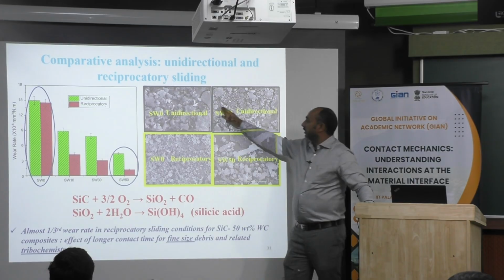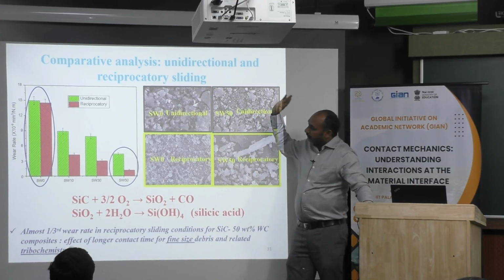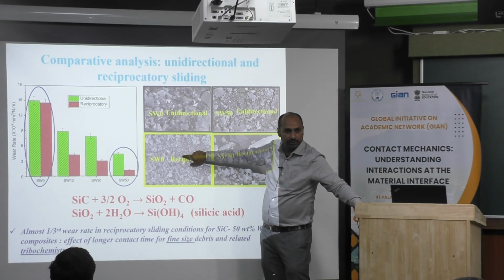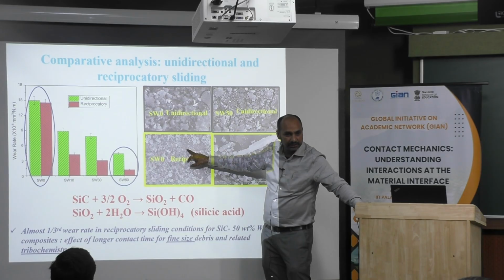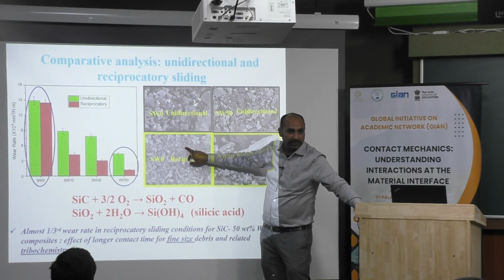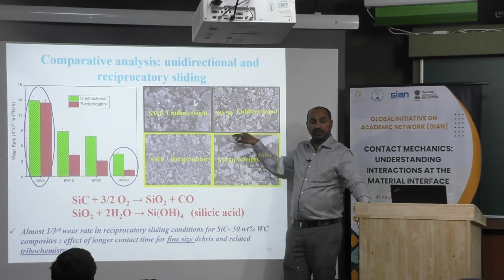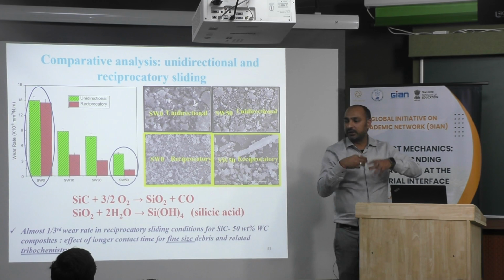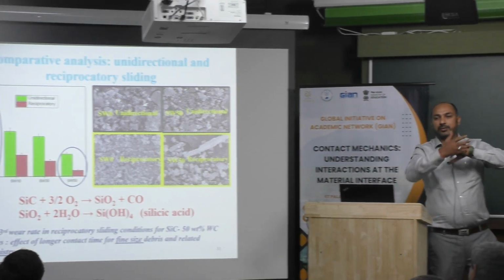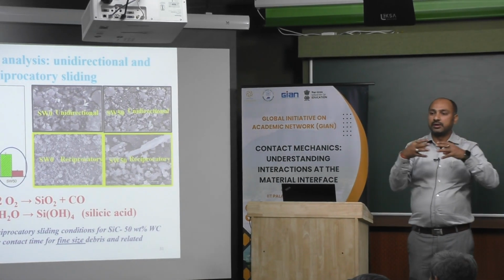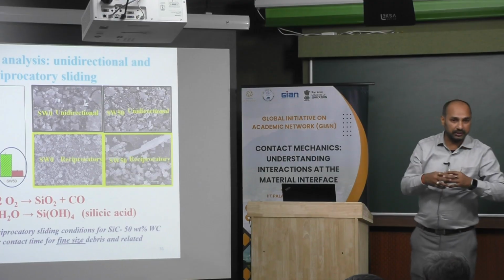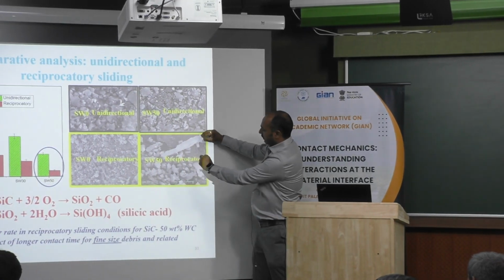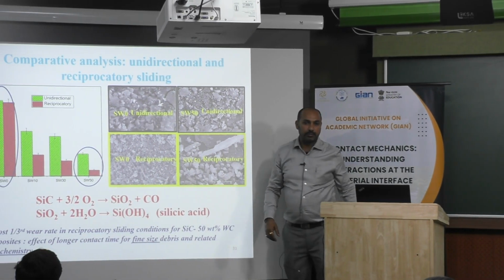We are simply seeing a reduction in debris size. Now by changing the configuration, the debris size for SW0 is decreasing, and it should decrease even further for SW50. Once they are very small in size, the surface area increases, and they try to agglomerate and connect to each other. With this particular humid condition, this is actually leading to cylindrical debris formation.